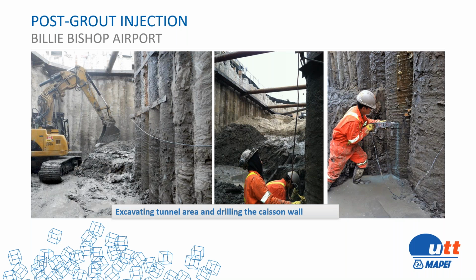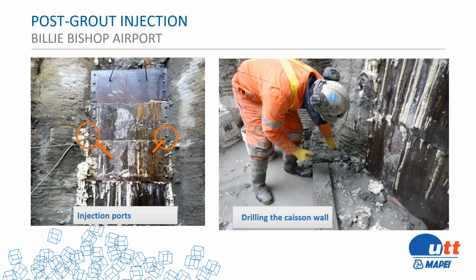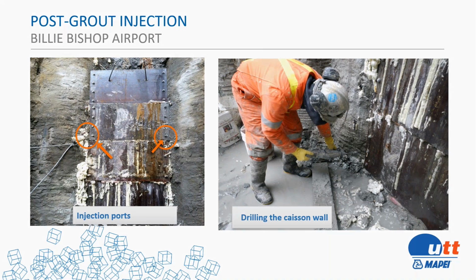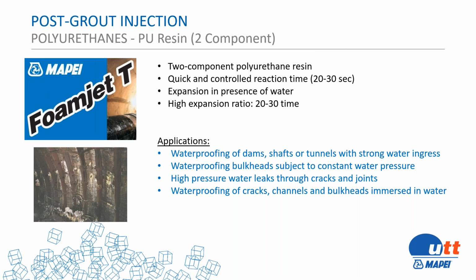Here's a picture of us using the Foamjet 1KM. These are caissons at the Billy Bishop Airport, and this is right outside of Toronto. And here they are drilling into the caissons. You can see where the injection ports are. This particular job was injected previously and had residual leakage, so we were able to incorporate the Foamjet 1KM and do a second injection without mechanically removing the first injection and stopping all the water. Next slide. The Foam Jet family.